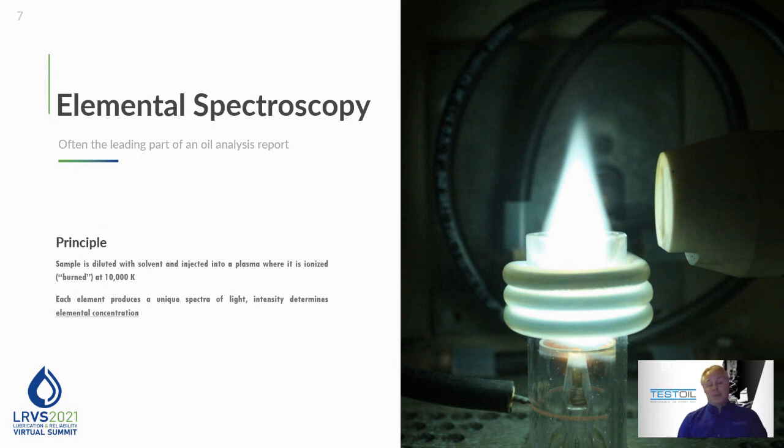So when we see just lead and tin, we don't know that it's brass or bronze. We assume it's something more like Babbitt, but as soon as we see the presence of copper, we can infer that that combination would represent something like brass or bronze. So that's kind of my point, is that we're only seeing the elements. We're seeing the building blocks. We don't see what, like I said, the chemical or the compound or the alloy of the metal might be.